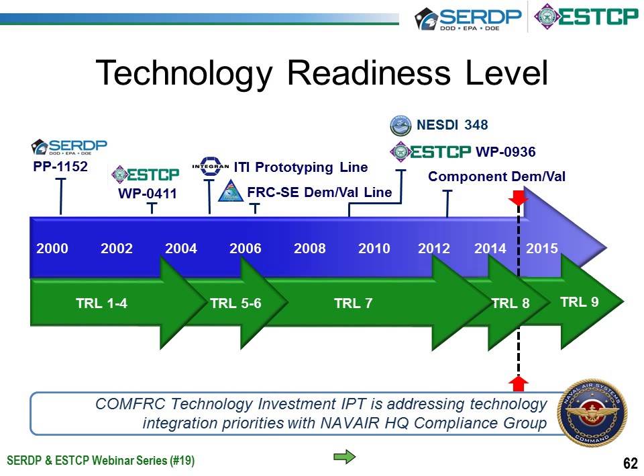So from a technology readiness level, these technologies take a long time to develop, and they go through many phases. All that we wanted to illustrate here was the amount of effort that has occurred from the beginning concepts under a SERDP to an original ESTCP 0411, which was responsible for establishing our demonstration line that we have here in Jacksonville. We then did preliminary testing and had to perform some supplemental analysis to control plating quality and to down select optimum plating parameters. And once that phase was complete, we then restarted as a new project, WP0936.